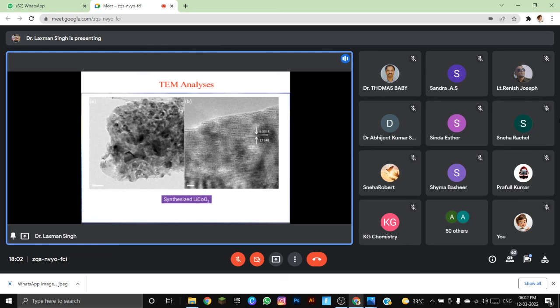This is the TEM analysis. Here we can see the particle size in nanometers. We also used the HRTEM picture for the d-spacing. This is the confirmation of the XRD 104 plane, and it means our material is a single phase material and has very good crystalline nature.